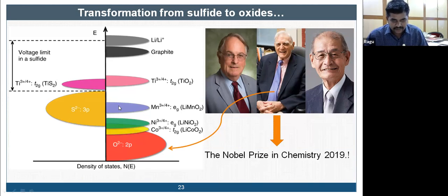So the idea is, instead of metal sulfide, use metal oxide. You can expand the potential window, thereby you can expand the energy density. So that was the idea. Slowly they moved from metal sulfide to metal oxide. This is the turning point in this technology, where they could achieve even 4.5 volt. Look at this: titanium disulfide was replaced with lithium cobalt oxide, the well-known cathode material. Almost 90% of our mobile phones contain these three materials: lithium nickel oxide, lithium manganese oxide, and spinel.